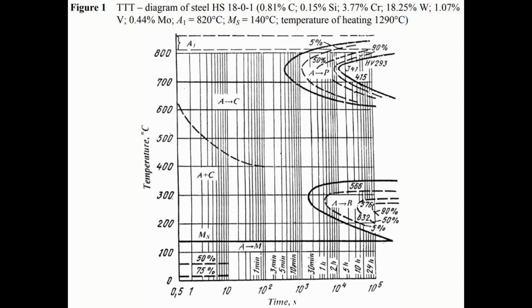Another thing to notice is that the hardness is also relatively low. So at that 500 degree Fahrenheit transformation temperature, it says it was about 576 Vickers. Looking at the conversion chart, that's about 54 Rockwell C. At the 200 Celsius line, that's about 400 degrees Fahrenheit, it says 632 Vickers, which is about 57 Rockwell. And according to this chart, it's not even clear that it was fully transformed to Bainite. So if you held it long enough to get full transformation, it may be even lower in hardness.